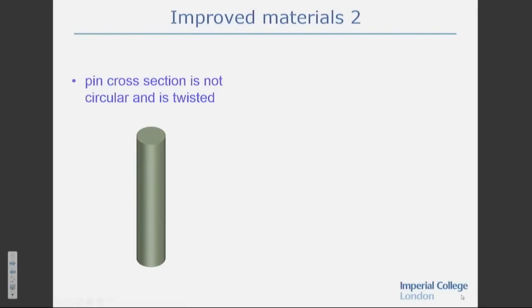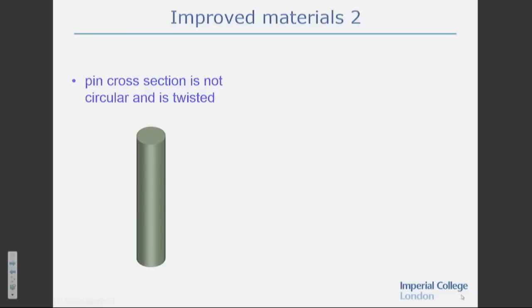But actually, the pins are not round. When we started doing pull-out tests on this, we found that actually they behaved rather differently from what we expected, and they absorbed considerably more energy than they would if they were simply round pins like this. What you'd normally expect to happen is the bond would fail, and then it would be resisted by friction as you pull it out of the hole in the composite.